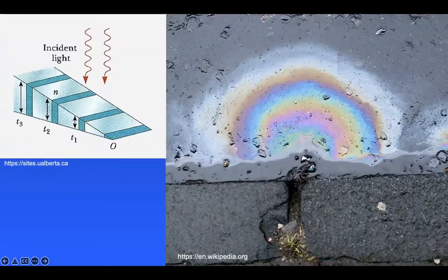And when we see these successive iterations, that might remind you a lot of what happens when you drop some oil onto water, and you can see successive sequences that are Roy G. Biv colors here. And the reason for this has to do with the change in thickness of that oil film, and that allows us to sample different values for n, in that n lambda equals 2d sine theta law that I described earlier. And so when that happens, we can see many different orders of constructive interference.